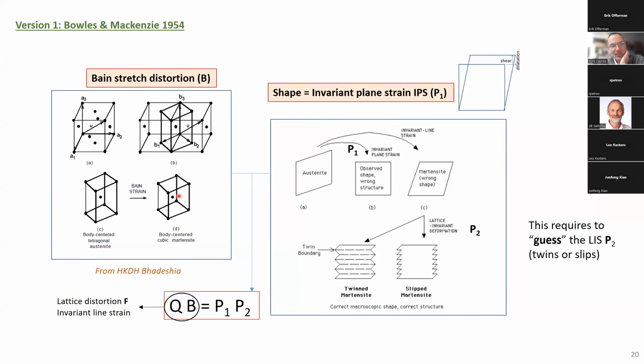I already explained that you can go from FCC to BCC by a contraction along these two axes and an expansion along the third, or by a contraction along this axis and expansion along these two axes. So this stretch matrix is also called the Bain matrix. The only problem is that the final orientation relationship between the FCC and BCC is not what we observed.